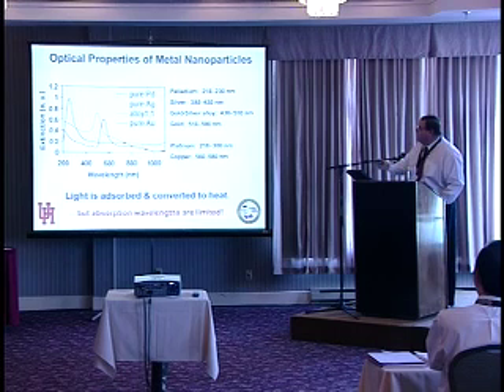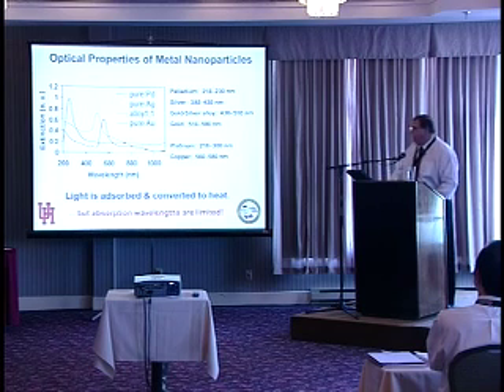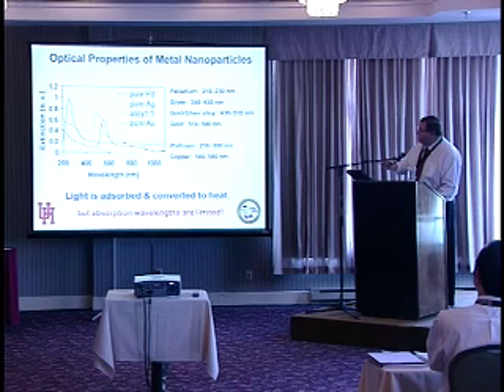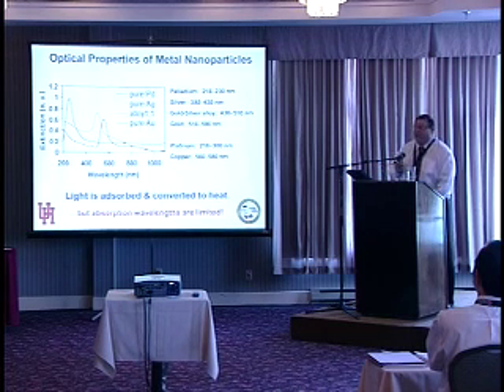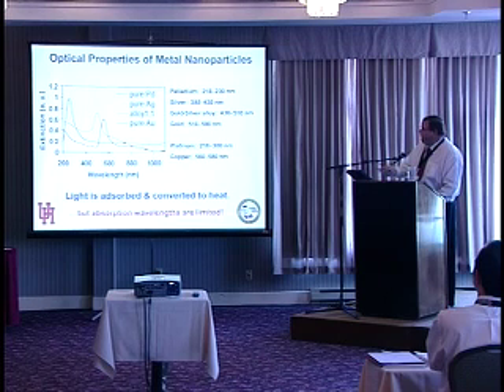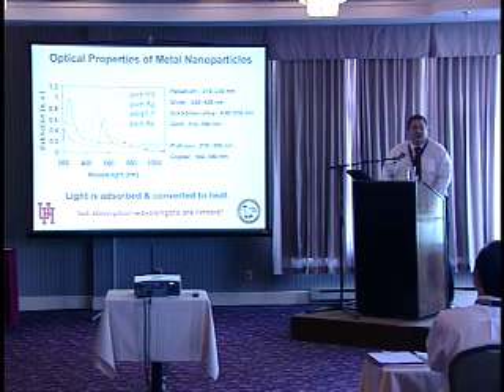So that's very useful. Unfortunately, the absorption wavelengths, however, are quite limited in what nanoparticles can encompass. For example, here is an absorption or an extinction spectrum of some metal nanoparticles. Palladium's plasmon resonance occurs just above 200 nanometers, silver occurs at about 400, and gold just about 500 nanometers. If you make an alloy out of gold and silver, then that plasmon resonance falls just in between that of gold and silver. So really, your absorption wavelengths with simple metal nanoparticles are limited to from about 200 nanometers to about, let's say 550 nanometers.